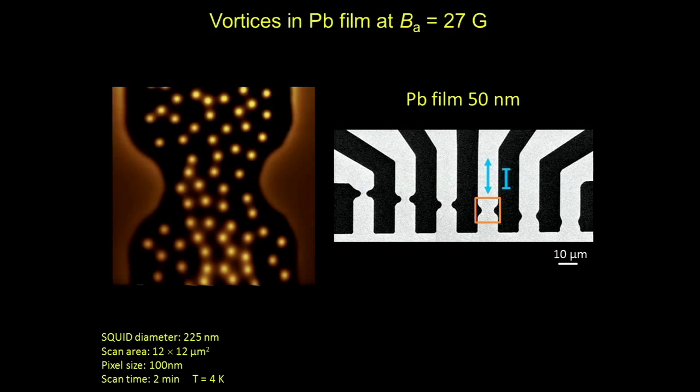Pinning plays a major role in many materials, but until now no one has really measured the interaction energy between a pinning site and a vortex. Each pin typically acts over a radius of about xi — the coherence length — and for lead that's about 50 nanometers. So to really map out the potential landscape of that interaction, you need sub-50-nanometer resolution. We probe our vortices using current: if I input a current in this constriction, each vortex will feel a transverse Lorentz force — I input the current vertically and the vortex feels a horizontal force.